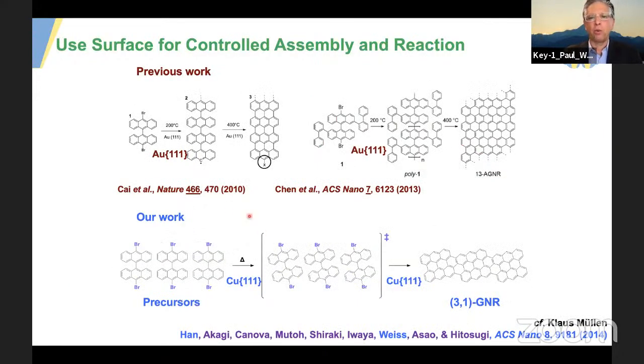And as I said, we knew a lot about this Ullmann coupling reaction, and so Patrick was able to design a precursor that would give him on the surface an intermediate that could then by reaction be zipped together to give these chiral graphene nanoribbons. And this is very much along the lines of Klaus Müllen, who's spoken at previous AVS meetings. He's really the star of this field.